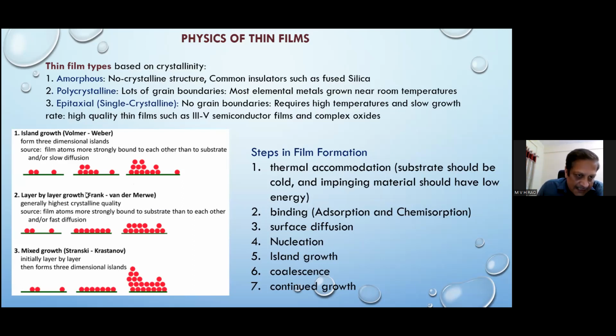Another is layer by layer. It's called the Frank-van der Merwe mode, as in ALD and MBE techniques, where layer by layer growth happens. First one layer, and only after that layer is fully complete will the next layer form. And in the other case, it is a combination. First layers will form, and after a few layers, islands will start forming. This is a combination of layer plus island, called the Stranski-Krastanov type of growth.